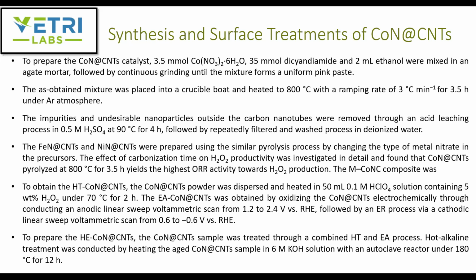And then they placed it in a crucible boat and heated it to about 800 degrees Celsius at a 3 degrees Celsius per minute ramping rate for about 3.5 hours under argon to get the final catalyst. And then, to remove any impurities or any undesirable nanoparticles outside the carbon nanotubes, they used acid leaching with 0.5 molar sulfuric acid at 90 C for 4 hours.